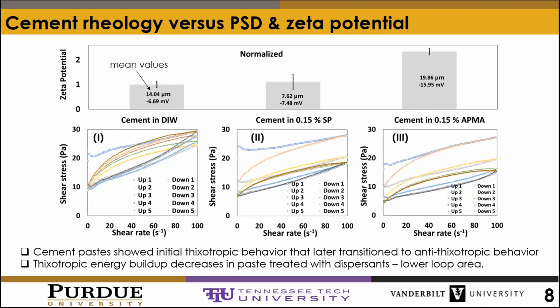So how do the particle size distribution and zeta potential measurement impact rheology? Dispersing agents do two things: modify the particle surface charges and the apparent particle size distribution. And in fact, changing both in different directions may have competing impacts on rheology. So what did we learn? Although the electrostatic charge on cement particles doesn't change with superplasticizer, as seen on the bar graph, the apparent size distribution reduces by half, indicating that superplasticizer sterically disrupts flocs.